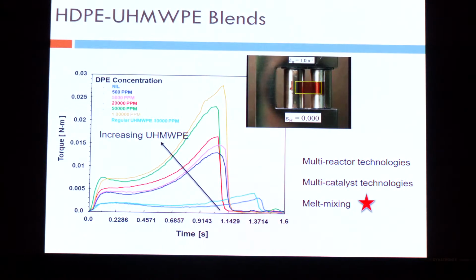Now, we were interested in looking at what happens when you start blending these two. So they are both polyethylenes. Chemically, they are similar. The difference is their molecular weight. One is about 2 lakh up to 5 lakh molecular weight. The other is an order of magnitude higher, 2 million, 5 million molecular weight. Okay? So what happens when you start mixing them? So remember this experiment that I said, you take a film, you melt it and you stretch it by wrapping around 2 drums. That's just a simple experiment. Essentially, you are stretching the film. Now, if I start putting a little bit of ultra-high molecular weight polyethylene in a lot of high-density polyethylene, and then start this stretching experiment, I see that with increasing amount of ultra-high molecular weight, the ability to stretch the film increases.